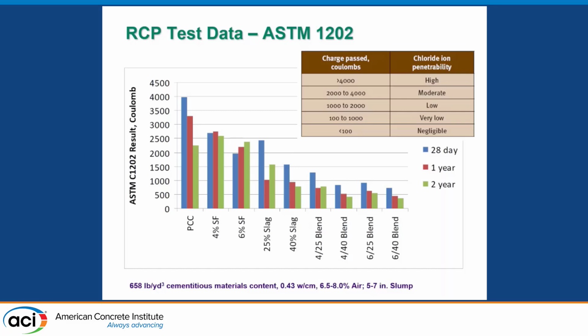And in Ohio, we salt our roads. We use some brine, we use salt, but obviously this is not going to be a very durable pavement. And so when we added 4% silica fume, it got better, and with slag we also saw that it was better. But when we actually got down to the blend, we were really seeing where we were going to see payback.